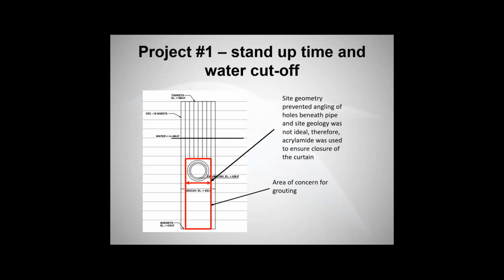But essentially what that was, it was a cofferdam structure within a river where a pipe was going to penetrate through the cofferdam structure. So you can see a pipe here. There's sheets which go around this pipe, but obviously you cannot drive the sheets through the pipe. So you end up with this window around and beneath the pipe for the cutoff structure. So in this case, this was through sand. Permeation grouting was chosen to make the seal around the pipe so that the cofferdam could then be dug out and the work could be done inside of it.